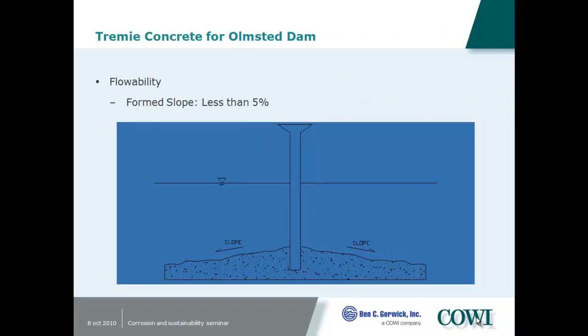As you see, it builds up around the bottom of the Tremie pipe, and it builds up a little bit of driving head to push it out. It moves out like a series of landslides. It builds up enough head, overcomes the shear strength of the fresh concrete, and slides out. And you build up another pile here as the concrete comes out, and it slides out and moves out laterally. So it's always moving concrete through the previously placed fresh concrete, and you always keep lifting up the pipe as you get up to the top, so that you're not placing through concrete that might be setting towards the bottom.